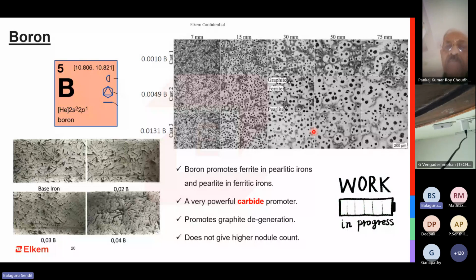It does not give a higher nodule count. There is some literature which says that if I have boron, it increases my nodule count. We have not seen that so far at Elkem, but we are still open and still working, and we can say quite confidently we do not see any evidence to suggest that it gives a high nodule count. The drawbacks outweigh the benefits here.